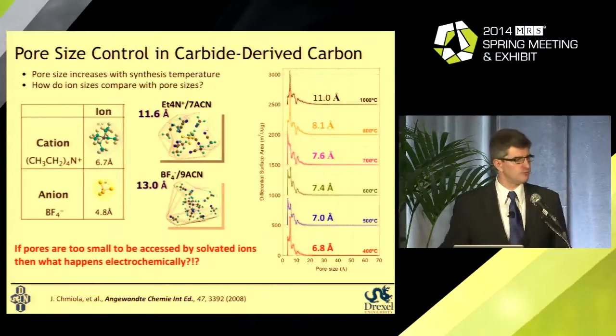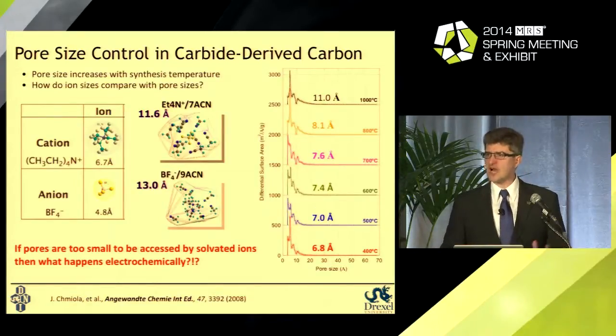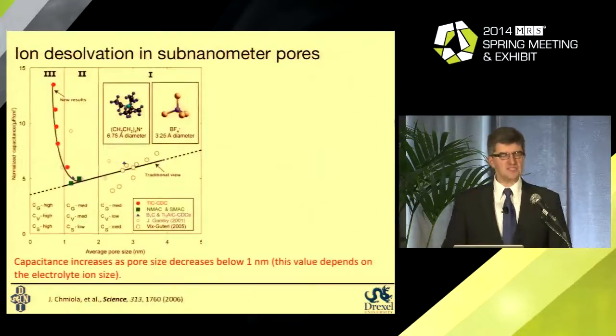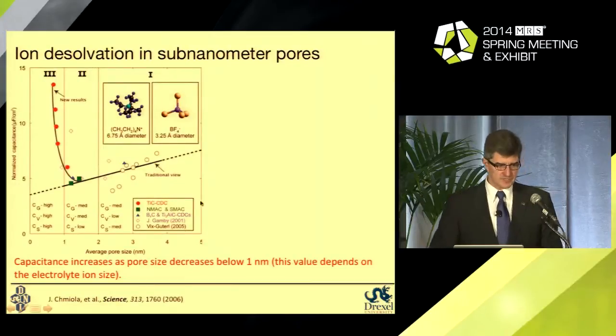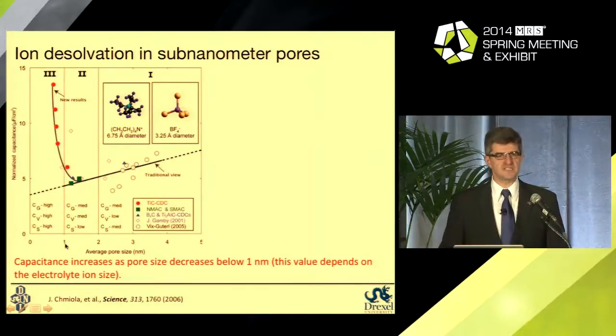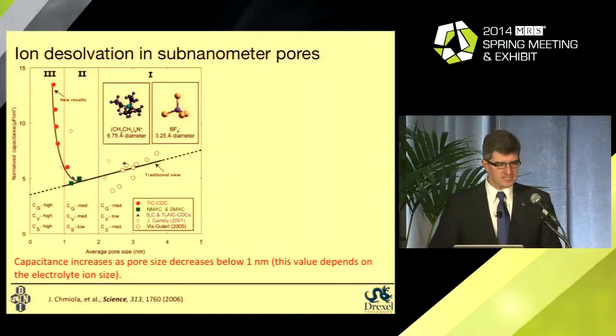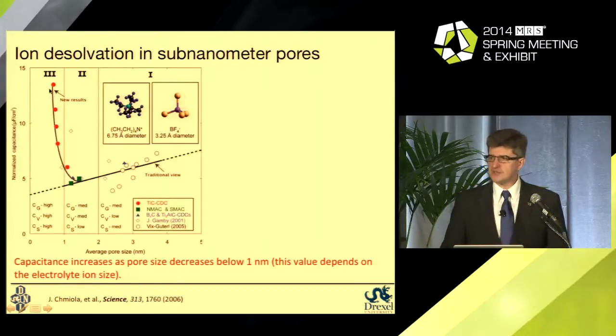We all know from chemistry courses that we took in school or college that ions are solvated in solution. And conventional wisdom was telling that ions go with solvation shell. They need to line up in pores, as I showed you in schematics before, to give you electrostatic energy storage in supercapacitor. And the result that we obtained was very surprising. We expected capacitance to drop close to zero at pore sizes approaching 1 nanometer because this pore size was smaller than the solvated ion size. But as a result, what we found is that capacitance actually increased, and increased dramatically, with decreasing pore size.